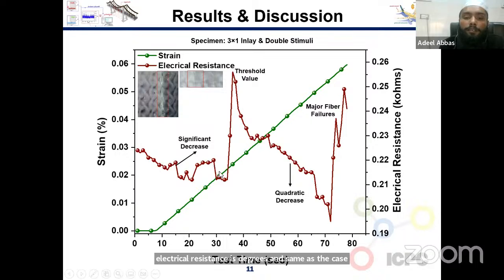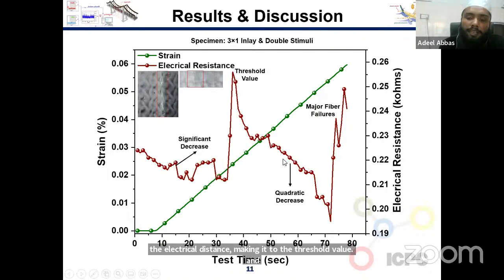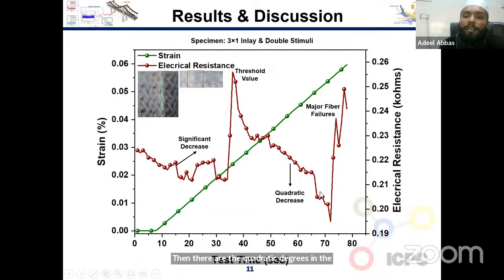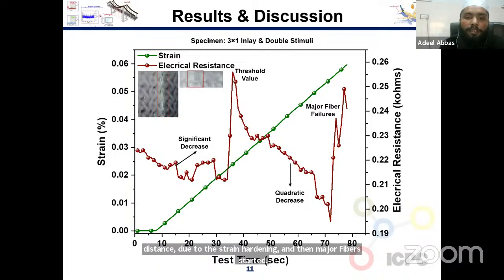However, after a certain time, there was an abrupt increase in the electrical resistance, making it reach the threshold value, and then there was a quadratic decrease in the electrical resistance due to the strain hardening, and then major fiber failure started, at which the composite lost its health.